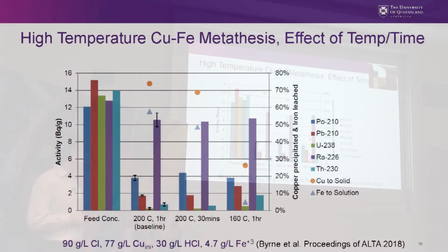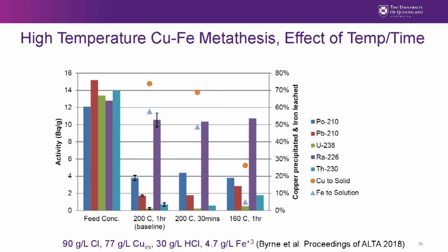So what's the message here is that it looked like 30 minutes or 1 hour didn't change the radionuclide profile too much. That's all close to experimental error. So that suggests we can go to a shorter time and still get the same type of radionuclide separation at 200 degrees. At 160 degrees, it looks like there's a little bit more lead remaining and a little bit more thorium. But if you look at the extent of the metathesis reaction for the iron-copper exchange, it dropped down a little bit with the shorter residence time, but it dropped down an awful lot as soon as you went down to 160 degrees Celsius. So for this process, it's pretty important to achieve those higher temperatures if you want to drive the reaction over there.